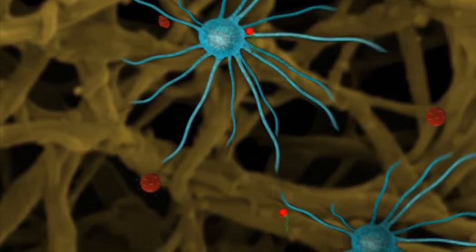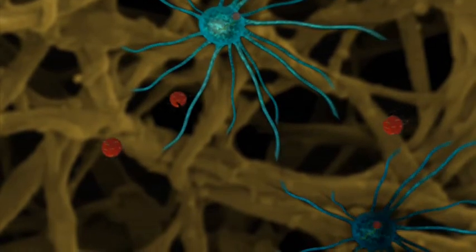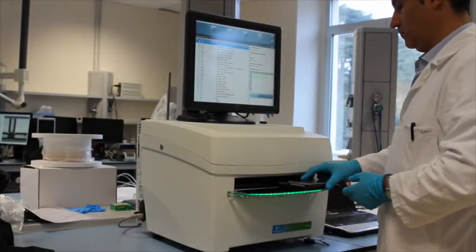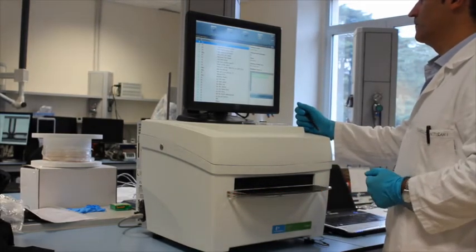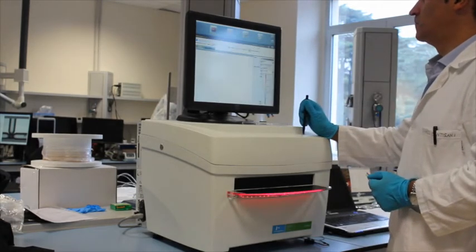The tumor-activated prodrugs were then tethered on the surface of 200 nanometer carboxyl-modified polystyrene nanoparticles. The resulting TAP conjugated nanoparticles were characterized for their in vitro release features at 37 degrees at different MMP2 concentrations to identify the minimum bioactive enzyme dose response.